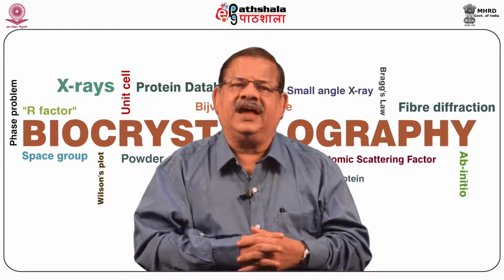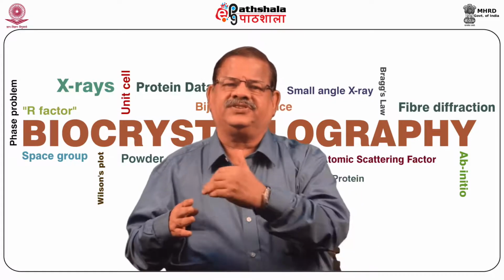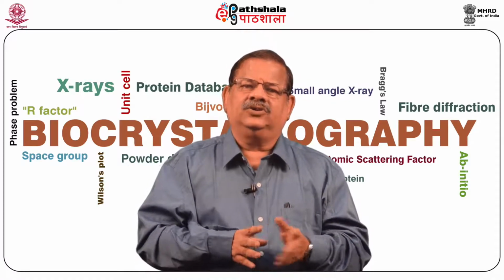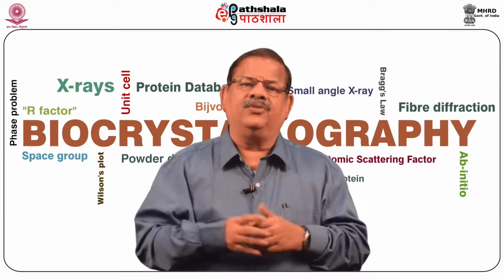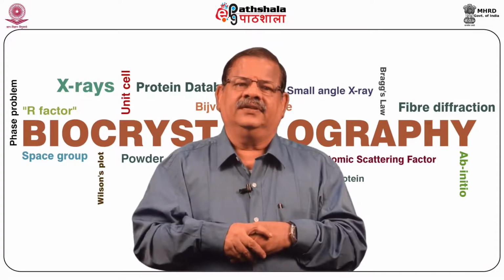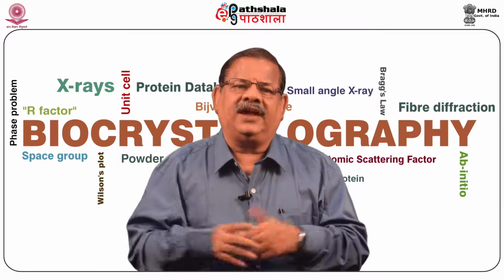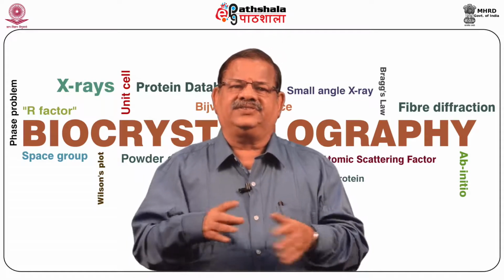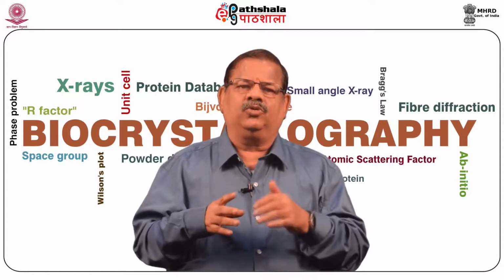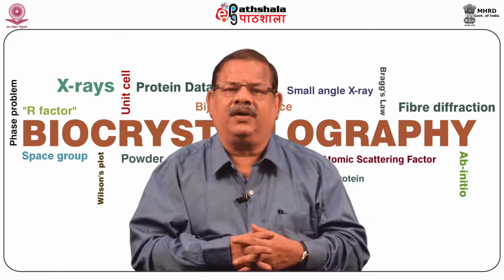If this length is L and capital R is the distance of the point of measurement from the specimen, the ratio of the energy in the length L to that in the whole halo is obviously L over 2 pi R sin theta, and hence the energy diffracted into a short length little l of the halo compared with the intensity of the incident beam is given by P over I, which equals p L Q V over 8 pi R sin theta, as given by equation 29.7.